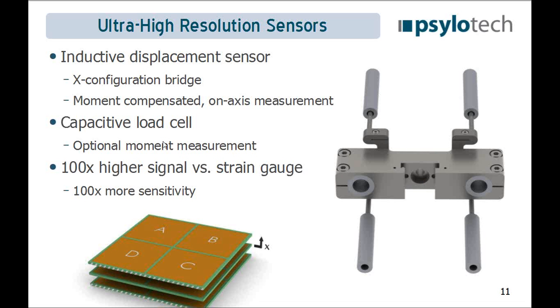Then we also have a capacitive load cell. Now the key to both of these, again, this is a capacitive load cell that is in a capacitive bridge instead of an inductive bridge, is that we end up with 400 or 500 millivolts per volt of sensitivity. We have much more signal to work with, but we condition it similar to the way one would condition a strain gauge, so we have over 100 times more sensitivity than a strain gauge, with similar electronics, so we're able to get more resolution out of the sensors.